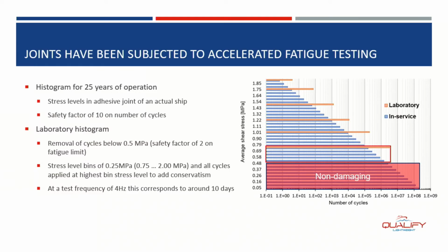We have to reduce the spectrum for laboratory testing. The first thing that we did was remove the cycles that we are quite sure are non-damaging. I had shown you a limit of 1 megapascal of shear stress in the joint specimens. We again applied a safety factor. We divided the 1 megapascal by 2, and everything below 0.5 megapascal has been erased. That's the non-damaging part. For the rest of the spectrum, we grouped all the blue boxes into a smaller number of orange boxes. In that red frame, for example, all the cycles are added to the highest level of stress, again to be conservative.